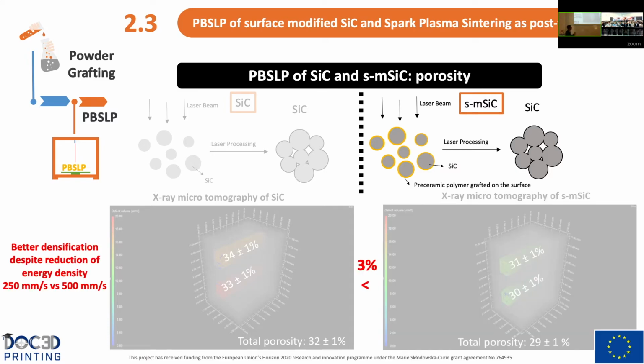So actually, here we are improving, we are decreasing the porosity by 3% by using surface modified silicon carbide. But remember that we are using 500 millimeters per second instead of 250. And I want to highlight that by using this scanning speed for the silicon carbide, we will obtain parts without reproducibility and with a lot of defects.